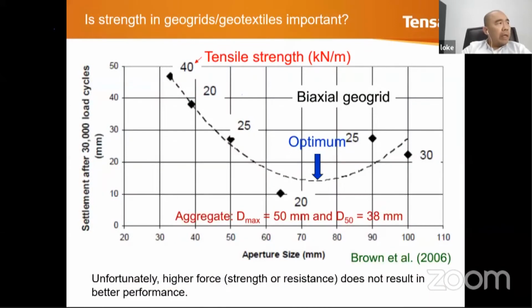And as I said, if the loading is not in the direction of the geosynthetic material, then strength is not the criteria. So if you look at here, we are using geosynthetic of different strength, 40 kilonewton, 25 kilonewtons, 20 kilonewton, 30 kilonewton, and so on and so forth. And we look at the settlement. After 30,000 load cycles, you can see that the lower settlement is around here, which means it is about 20 kilonewton tensile strength of the geosynthetic. Compared to a 40 kilonewton strength geosynthetic, it gives you a huge settlement. So strength is not the criteria, okay?